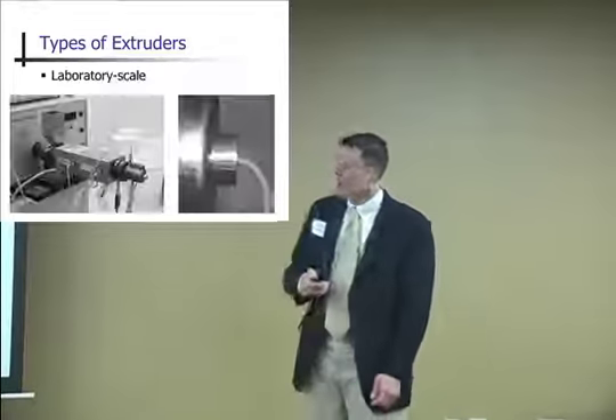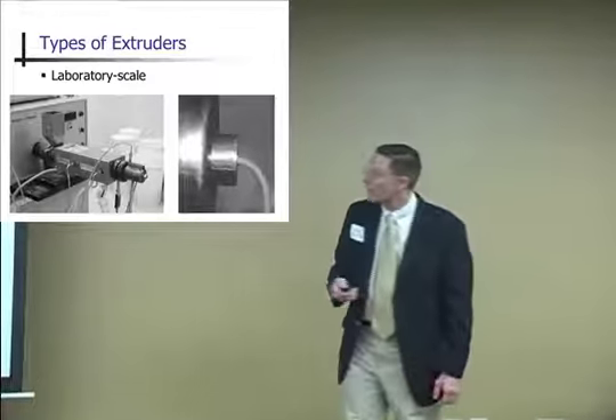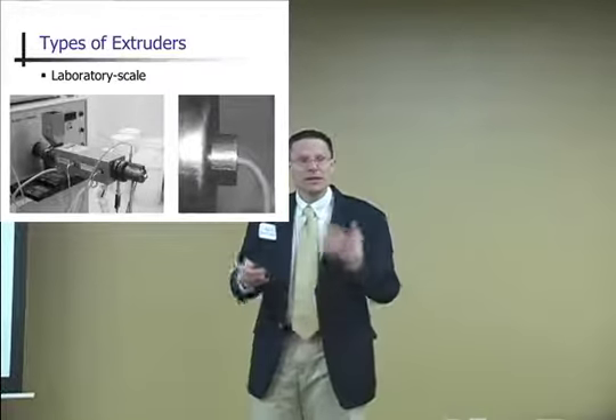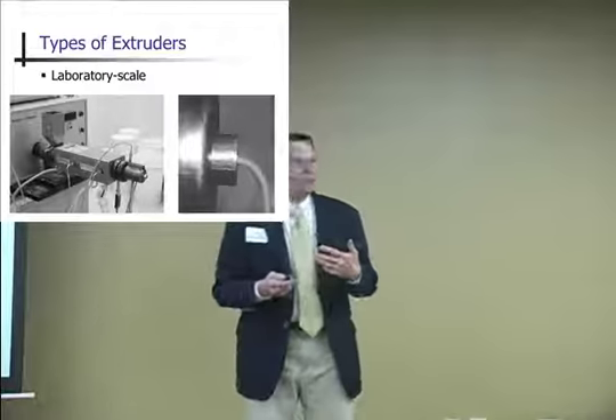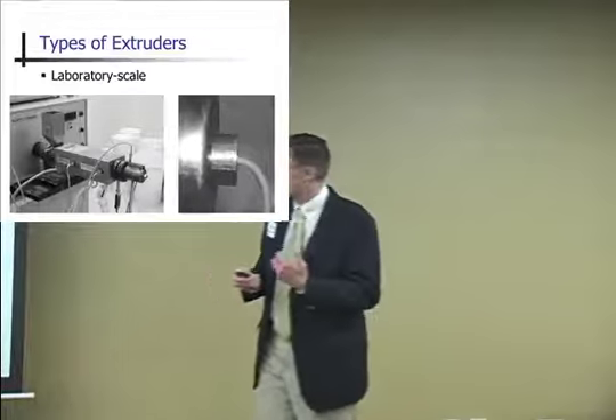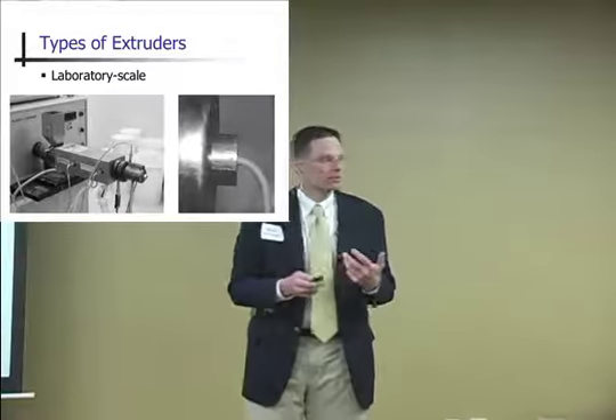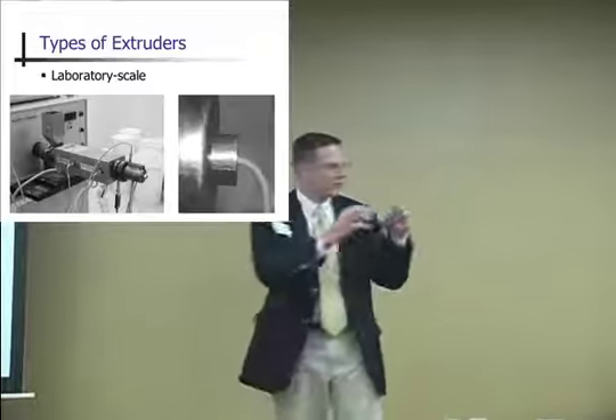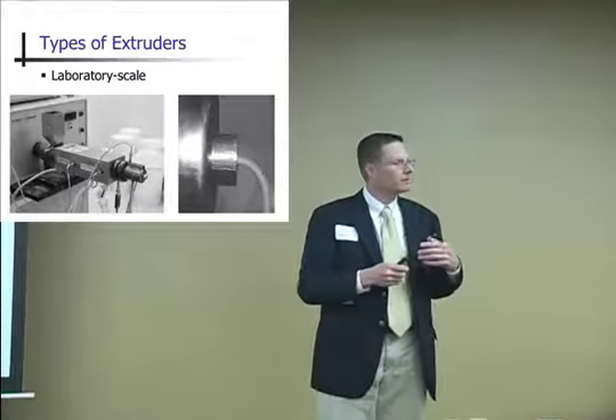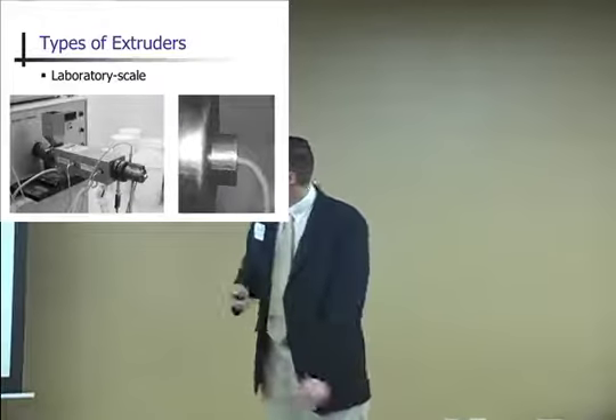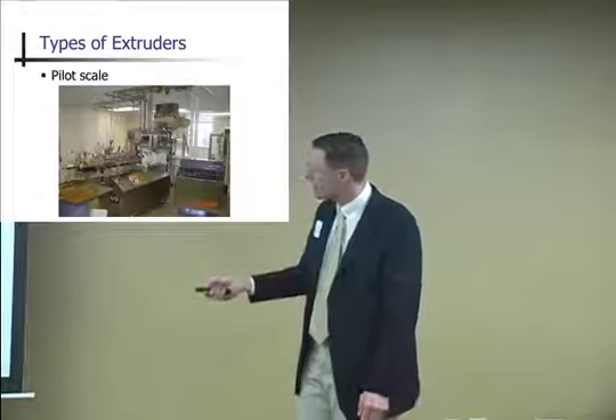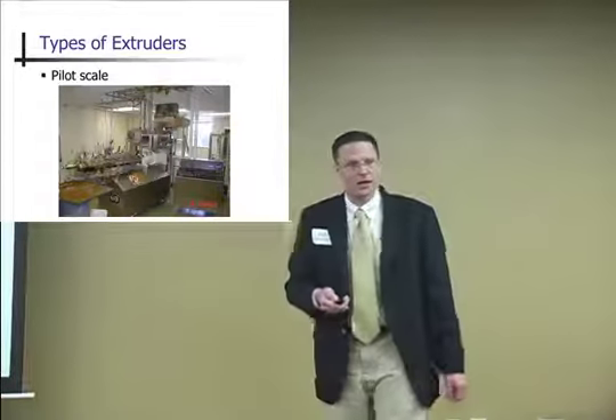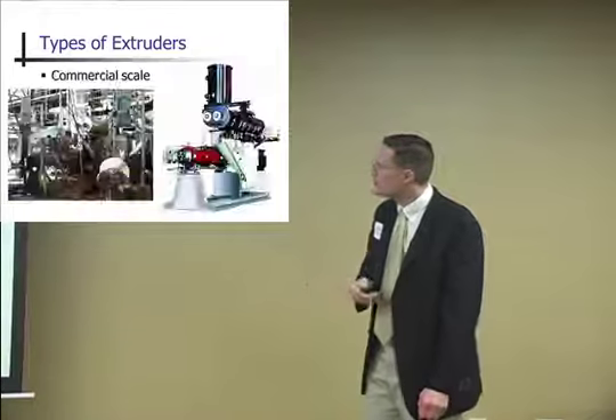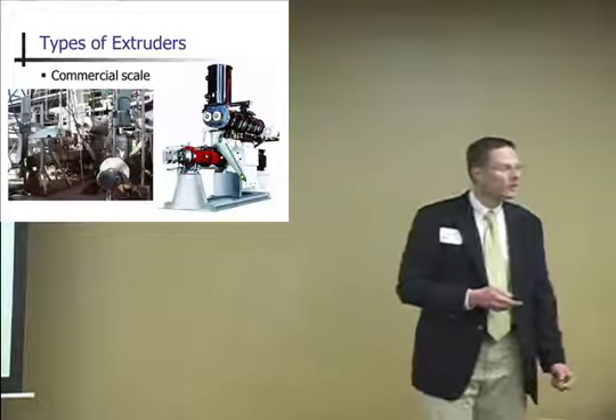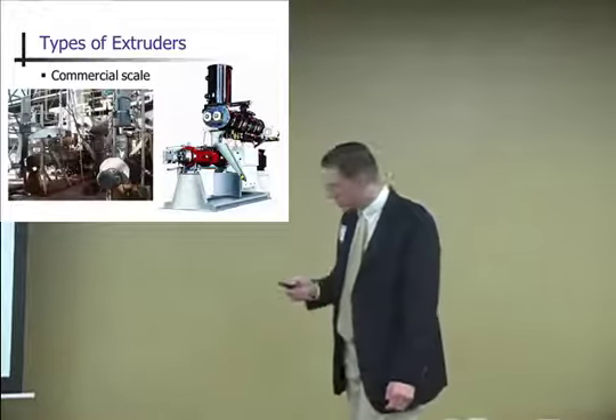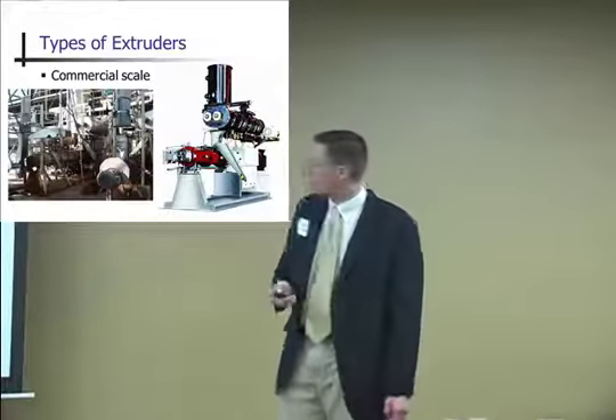So you can think about laboratory scale extruders, which are great for experimental diets. A lot of experimental diets are made with like a Hobart sausage grinder. The thing is, you don't get any temperature increase with those. Or if you have KitchenAid mixers, you can also get the sausage grinder attachment for your KitchenAid mixer. But you don't get any cooking, any temperature increase. So pilot scale extruders, we've done a lot on the Wenger system. Gives you a lot better flow rate, a lot better temperature control. But then you have the commercial scale. You think of the feed mill side. The feed mills are generally going to have larger systems than the pilot scale systems.